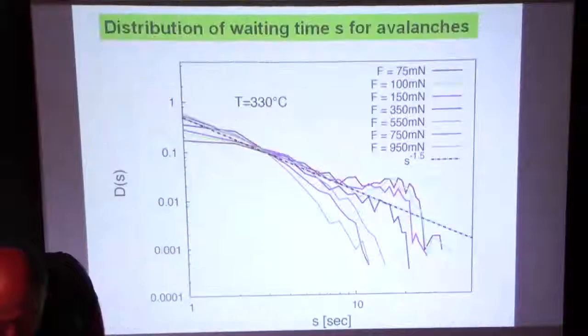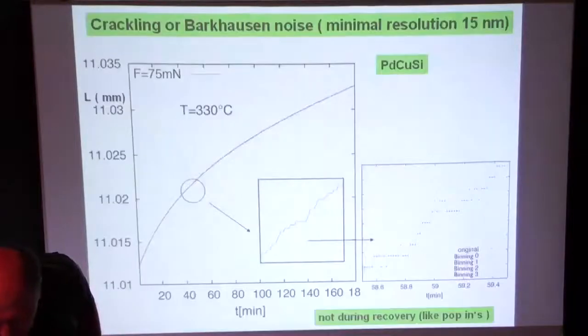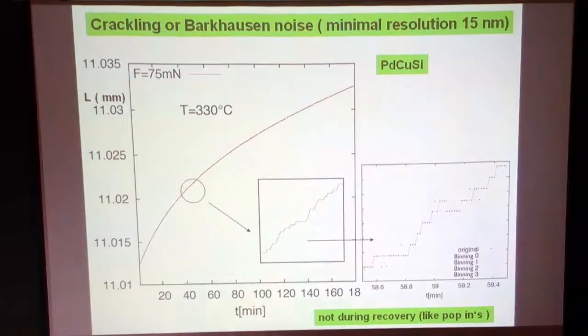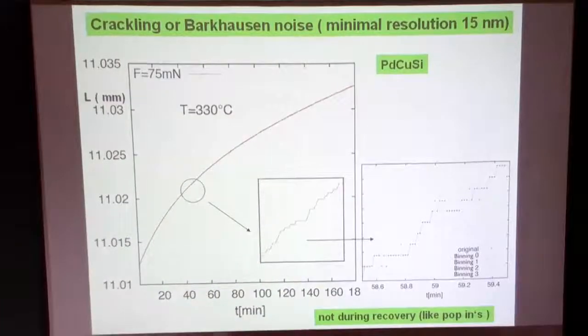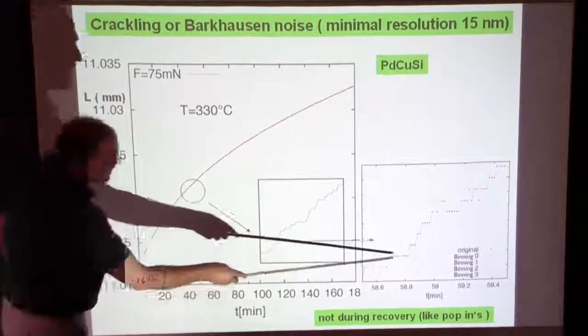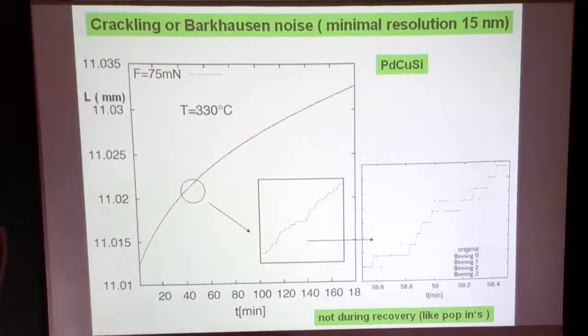Well, that's the point. We cannot do the statistics of those systems here by different length scale jumps. Normally, if you follow Karin's suggestions, you would say, okay, what kind of slip lengths you have for different stress, and this is limited in our case mechanically to that kind of resolution. So the idea could be, okay, you take this kind of steps and call that one avalanche if you bin it this way. Okay, that's possible.